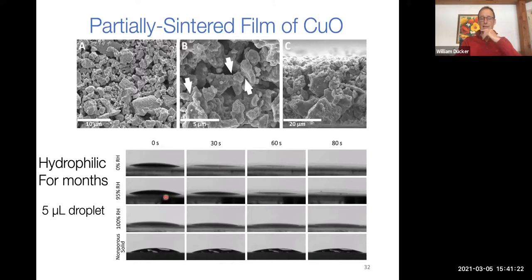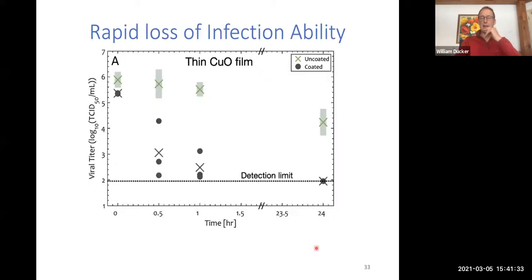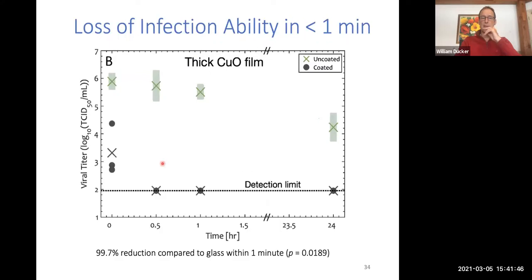Even at 95% humidity, which is about the most humid conditions you get, you know, it gets down there in a minute. Compared to if you have a non-porous solid, it's just sitting there waiting to evaporate in the same time. So we looked at the inactivation of a thin film of cuprous oxide where the droplet doesn't go in completely. It inactivates the virus pretty well in half an hour, which is an improvement. But if we make a thick film, so the droplet goes right in, so by thick, I only mean like 50 microns thick. It's not that thick.